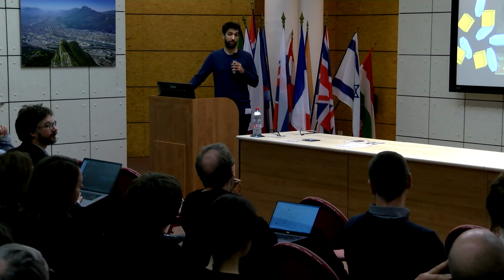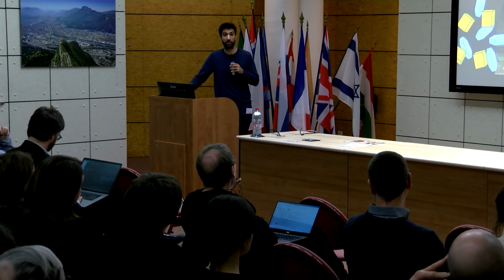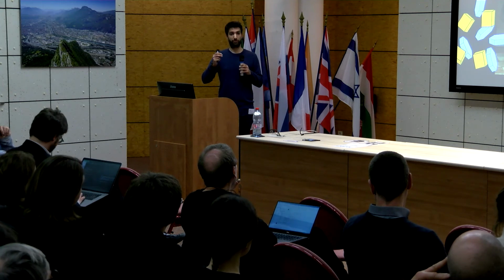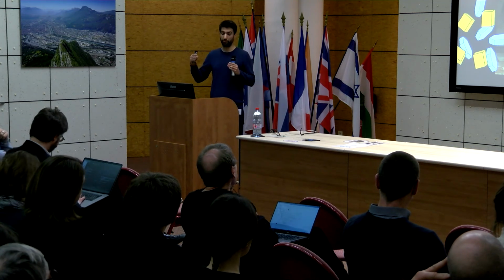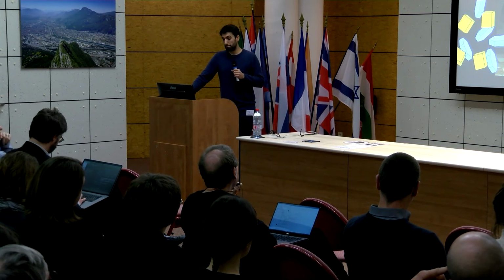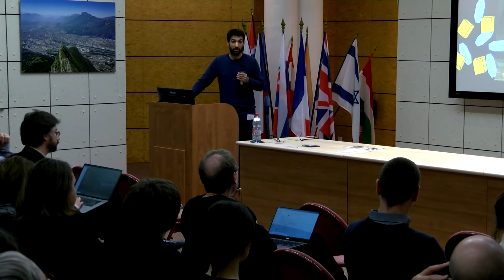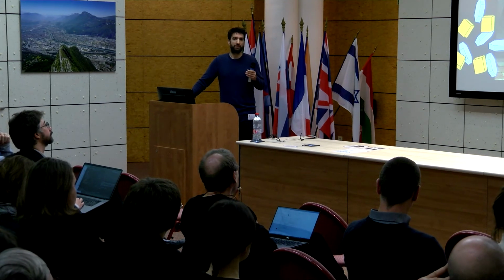That's absolutely indeed a working hypothesis. For example, in the case of impasto, there is now a new project being developed at the Rijksmuseum where it will be more focused on, for example, the morphologies of crystallites, and if this has something to do with the rheology. So there are different routes to approach this problem. Basically, the fact that plumbonacrite is present means that something is alkaline. So to us, this was the most obvious answer, this litharge-based oil.